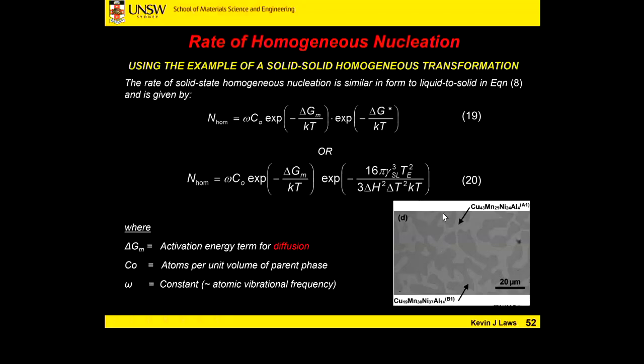Now what we see in terms of our holding time, at an annealing temperature below that transformation temperature, which is about 900 degrees centigrade in this system. We hold this at 850, very close to that transformation temperature, but below it, so it's going to happen. Over time, the secondary phase volume fraction doesn't change, but the shape and morphology does, as it tries to minimize its surface area.